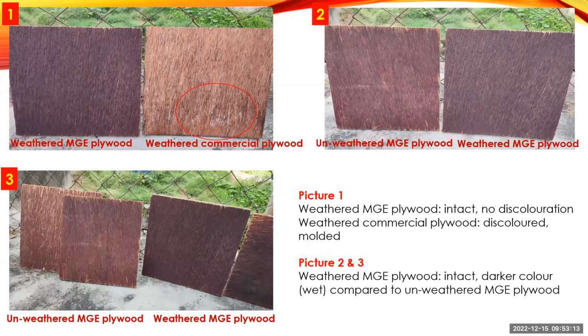The plywood has been subjected to 3-month outdoor exposure. Comparing the weathered resin treated plywood to the commercial plywood, we can see the commercial plywood already has discoloration and has been moulded, but the resin treated plywood stays intact and the surface still looks very clear and nice.